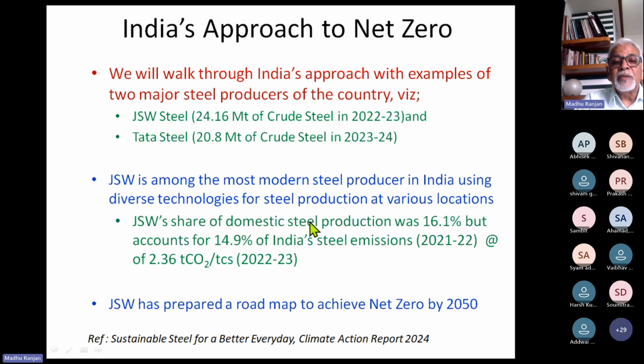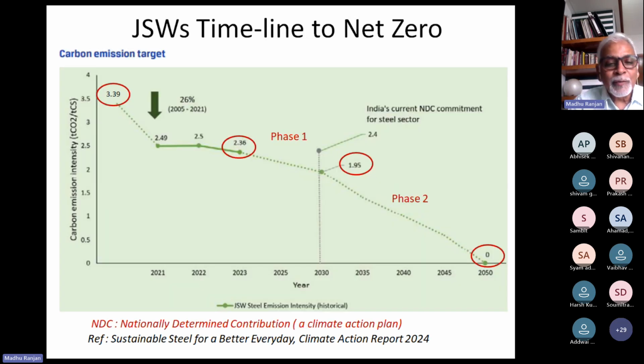The JSW share of domestic steel production was 16.1% of the total steel produced in India in 21-22, but they account for around 15% of India's steel emissions. So they are slightly better than the all India average. The present emission rate is around 2.36 tons of CO2 per ton of crude steel. So we will go through the roadmap prepared by JSW. Since I have a background of JSW, please don't mind. I'll be referring to this company's data, and I'm thankful to JSW for sharing the data with me.